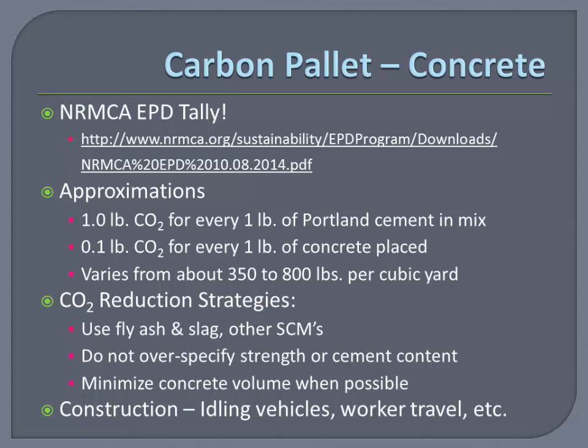We typically start at about 20%. All of our concrete, pretty much all of our concrete, has a 20% offset of the amount of cement with supplementary cementitious materials. We're only scratching the surface on some of the ideas that we've developed in more detail, but to not overspecify the strength, to use 4,000 when you don't need 4,000, and to minimize the amount of concrete volume when possible. For example, using frost-protected shallow foundations instead of deep 4 or 5 foot deep foundations can make a big, big difference, and we'll talk about that in a minute. There's a downside to any field operation, including construction: diesel vehicles idling, worker travel, etc. But that's kind of concrete in a nutshell.